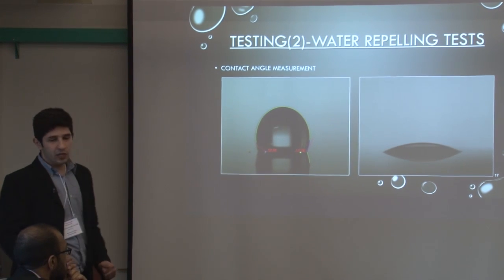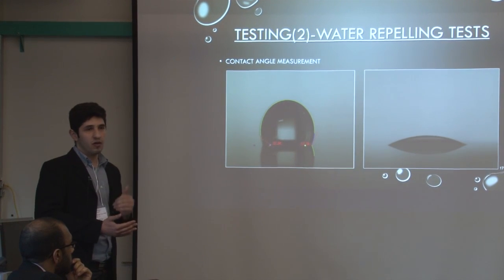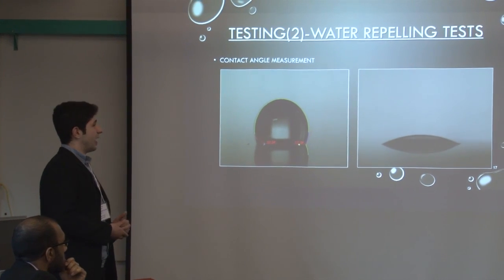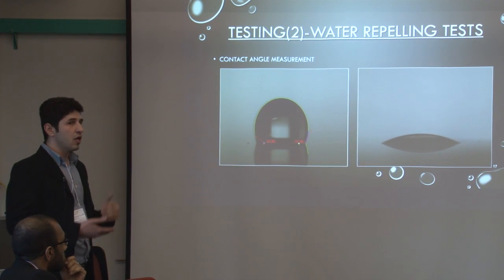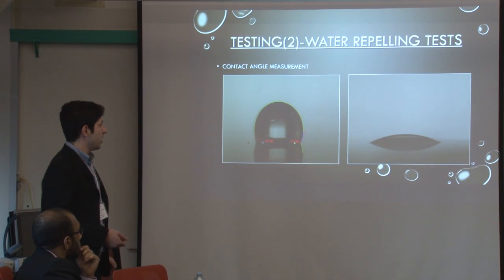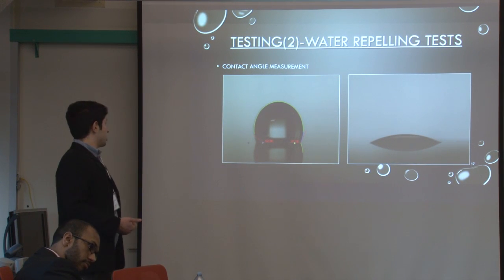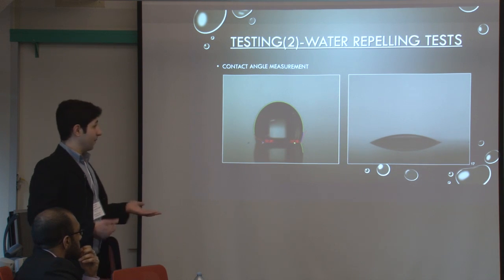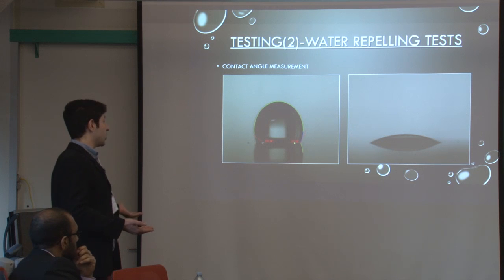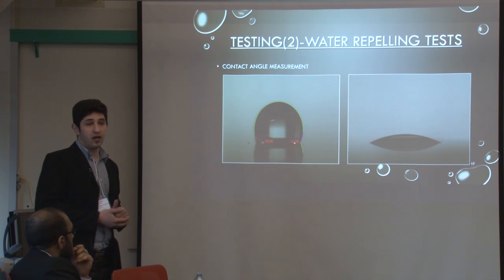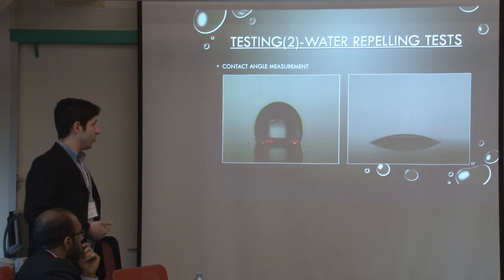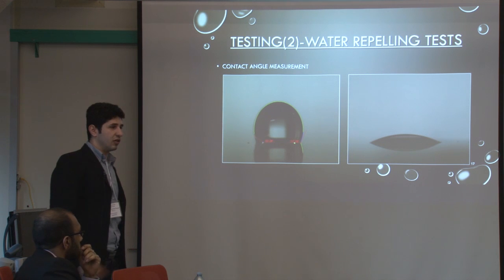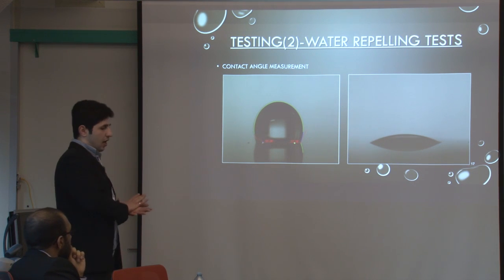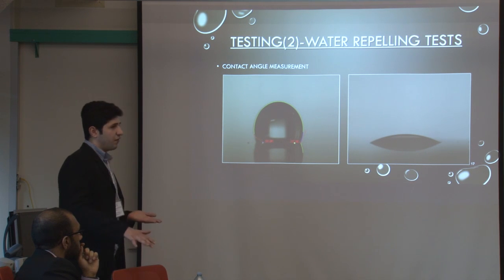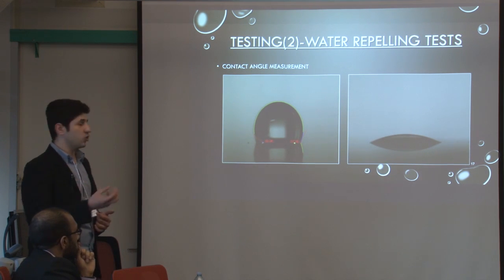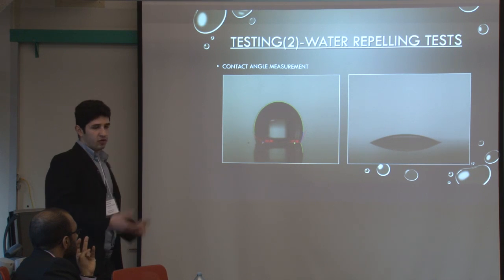Now that we know that we have our nano pattern design on the surface, we needed to make sure that we were able to achieve a high contact angle when the water droplet or the oil droplet is placed on the surface. The picture on the left shows a modified, patterned surface, and the picture on the right is just a glass substrate. As you can see, we're able to obtain up to 151 degrees of contact angle, as opposed to the picture on the right, which gives us a maximum of 20 to 30 degrees. So the water basically flows on the regular surface, as opposed to our surface where the water forms a droplet with hopefully an air packet underneath it.